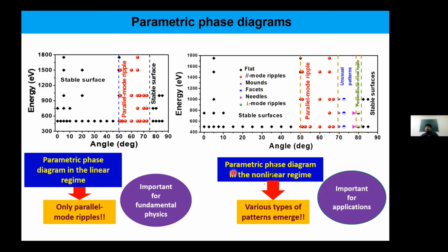But what we get to see in the nonlinear regime is parallel mode ripples. Then we get to see unusual patterns like needle-like structures or evolution of facets and so on and so forth. And then perpendicular mode ripples. So all these things belong to the nonlinear regime. And these patterns that evolved in the nonlinear regime, including these ripple patterns, can be very useful for different applications.